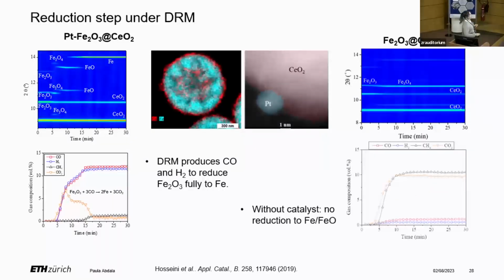This is how the material looks by electron microscopy. So you have the core of iron or iron oxide, the shell of ceria. And if you go into higher magnification, you see the platinum nanoparticle. The proof of concept is here.